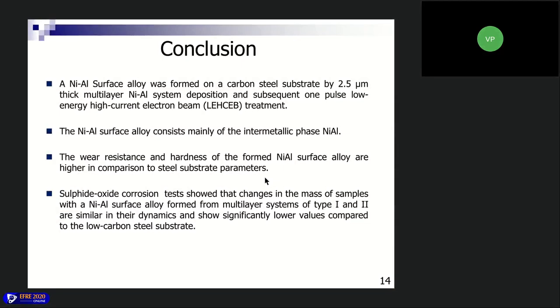So in conclusion, I would like to say that the nickel aluminum surface alloy was formed on the substrate. We achieved the desired thickness of 2.5 micrometers. We did it with different systems.